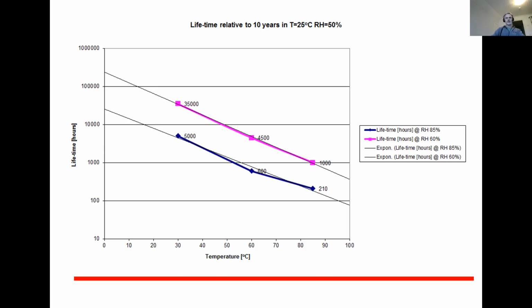And now I have here 2 lines. This line here in purple color indicates the test time needed if the test relative humidity is 60%, and on the x-axis we have testing temperature. And this dark blue color indicates that if we increase the relative humidity from 60% up to 85%, we can see the acceleration here with the same temperature. So this is how one can estimate the combined effect of temperature and humidity on the acceleration.